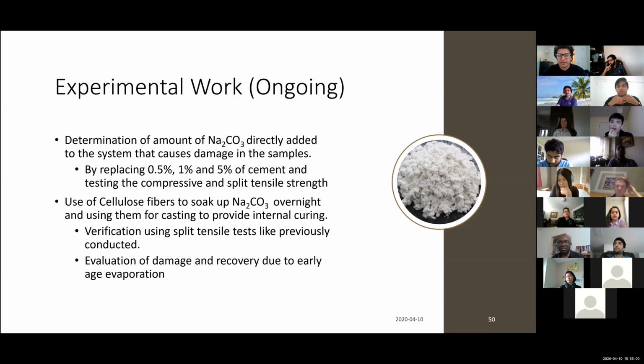Yeah, so that's a real concern. If you have the unhydrated cement and you leave it in sodium carbonate, then that starts to react directly with all the unhydrated particles and affects the hydration. So how are you quantifying that? That's a tricky thing actually. The last test that we were doing is to see what percentage of the sodium carbonate starts to degrade the performance of the concrete.